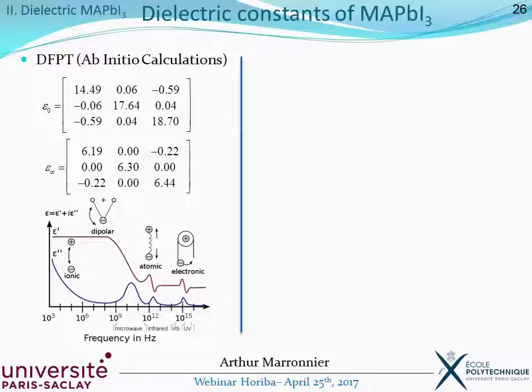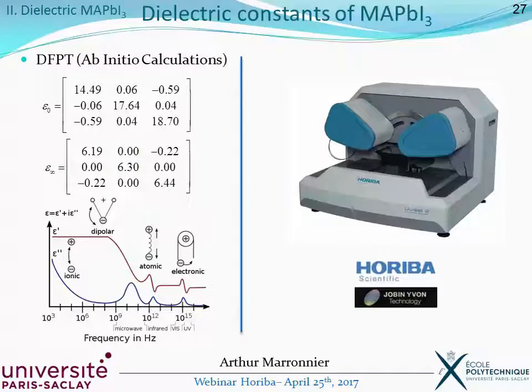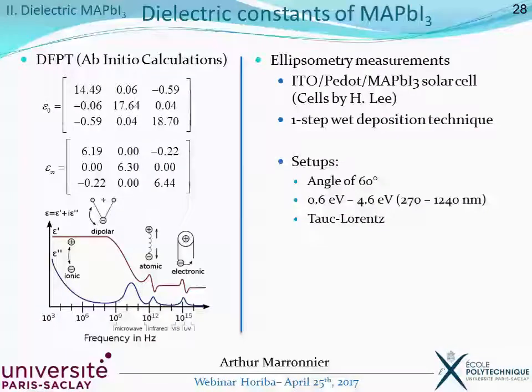electrical transport characteristics. Now, in the high frequency regime, we can compare these results with ellipsometry measurements that we did in collaboration with HORIBA using this ellipsometer and making our own cells at Polytechnique. So they were made on top of glass, ITO, and then we used PEDOT as an organic hole transporting material and the main absorbing material, methylammonium lead iodide. These cells were made using the one-step wet deposition technique.